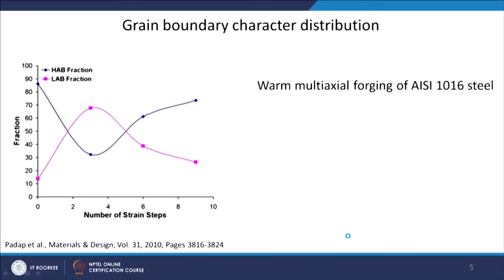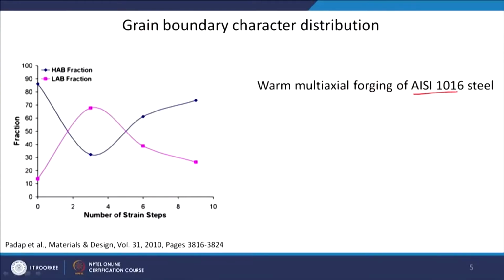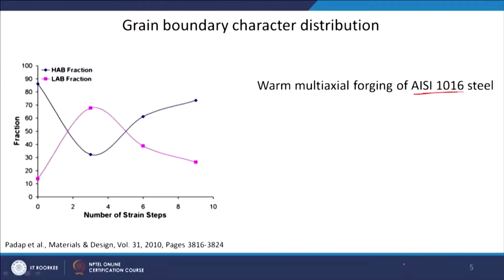So, when you are having all this microstructural change, for example, this work was on warm multi-axial forging on a plain carbon steel. And as you can see, initially the grains are dividing into subgrains. So, obviously, there will be an increase in the fraction of low angle grain boundary. And later on these low angle grain boundaries are getting converted into high angle grain boundaries, which can be through any of the CDRX mechanisms, grain rotation or conversion of these low angle grain boundaries through continuous recovery of dislocations into high angle grain boundaries and so on. So, there are multiple mechanisms of CDRX. All these mechanisms will operate, and different mechanisms are proposed for different materials.